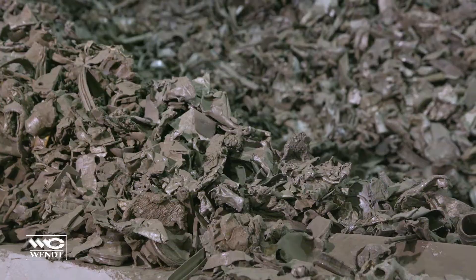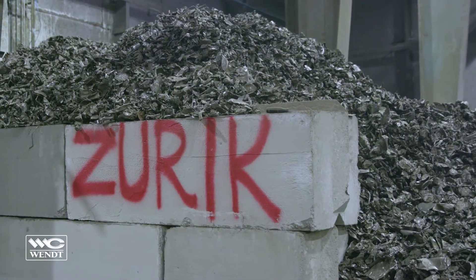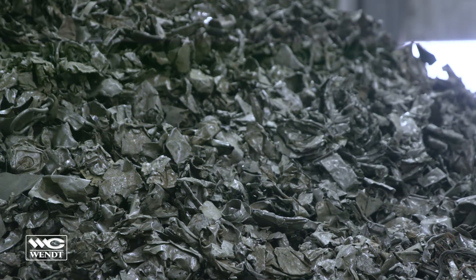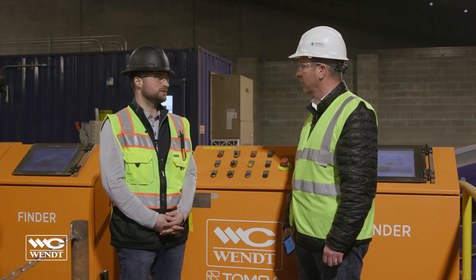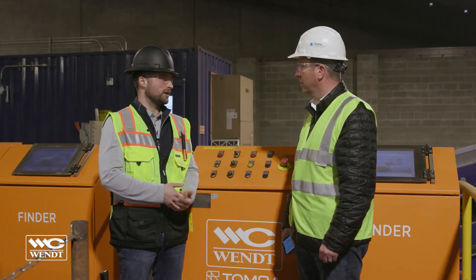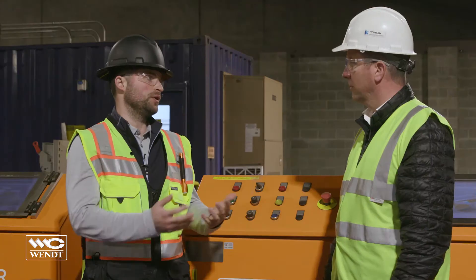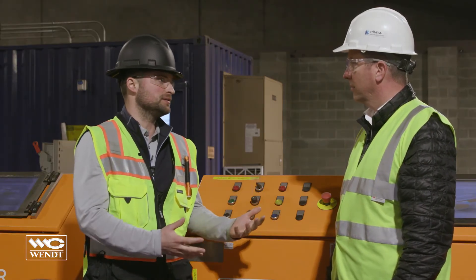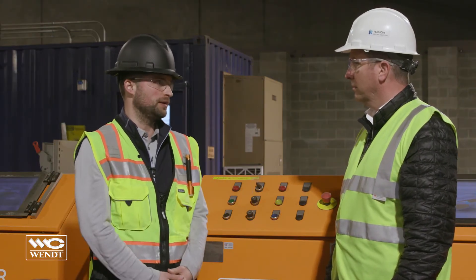What finished products are you making, and what purity and throughput rates are you getting? We're making a Zurik shredded stainless, which is almost 100% recovered shredded stainless. We're making a shredded wire package which roughly recovers in the 40% range. And then we're making a Zebra heavies small shredded wire package that is about a 60-ish percent copper rate with some other metals mixed in.